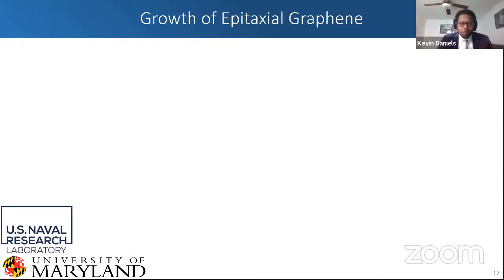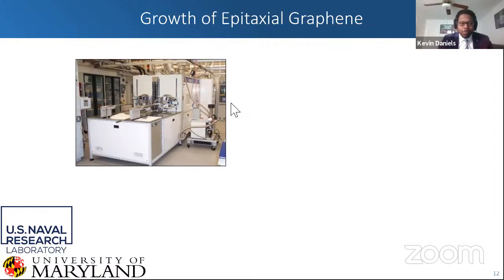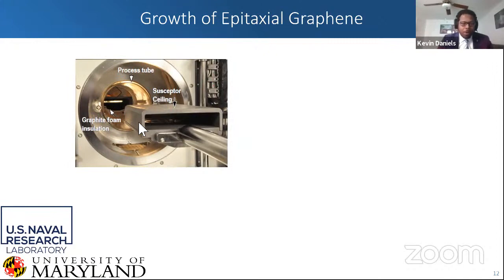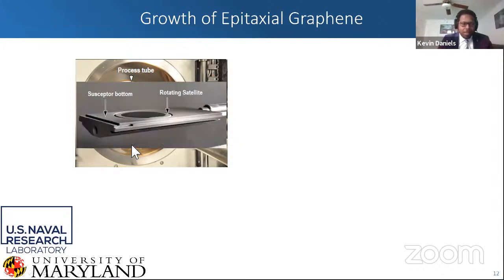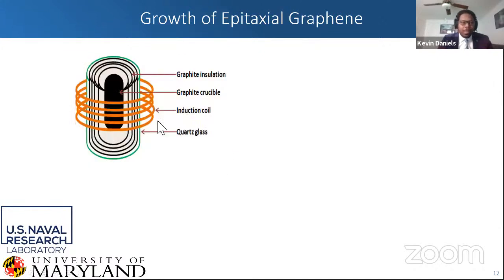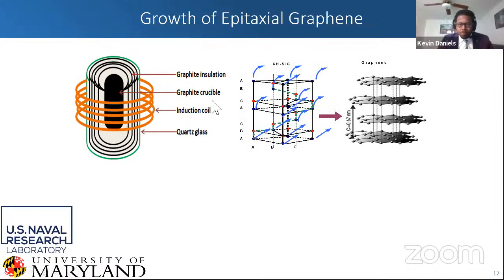So I did my postdoc at the Naval Research Lab, and I focused on this growth of epitaxial graphene. This is the CVD reactor here. The first chamber on the right is used for silicon carbide growth, but the chamber on the left is used for the synthesis of graphene from silicon carbide. Here is the chamber. It's all graphite here. We have our 4-inch wafer sitting here that rotates in the chamber. Again, it's all made of graphite because we're heating it inductively. So we induce eddy currents into the chamber, and our sample heats up as a result. And we heat it up to around 1580, 1600 C.